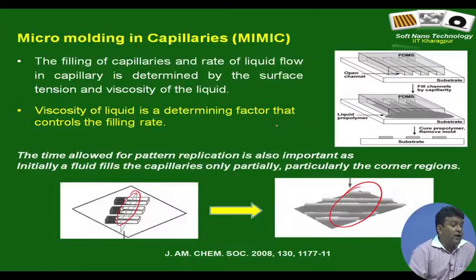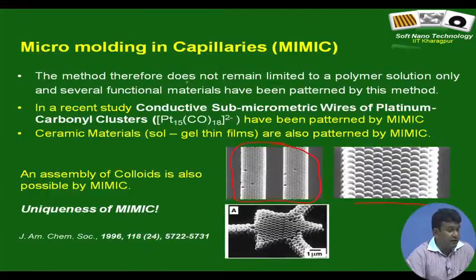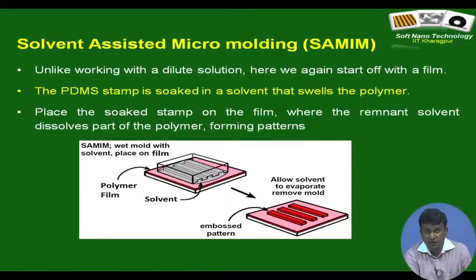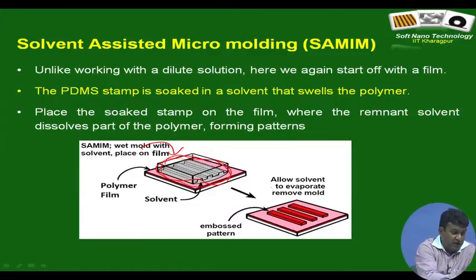It circumvents some of the basic problems of MIMIC by taking some clue from nano imprint lithography and other techniques which start off with a pre-existing film. So, what you do here, instead of MIMIC, where you start off with a bare substrate, there is no film, you are back to a spin coated film in SAMIM, just like nano imprint lithography. You take the stamp and wet it in a solvent of the film. As you place the stamp on the film, locally the solvent that comes along with the stamp reduces the viscosity of the film in the periphery of the stamp, and in presence of the stamp, due to capillarity or due to any force you are applying, the polymer reorganizes along the contours of the stamp pattern, and you get some nice patterns.